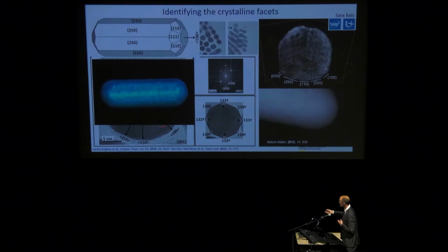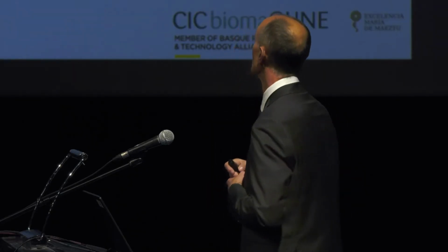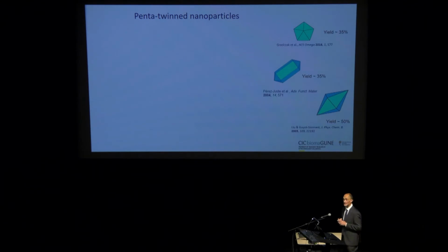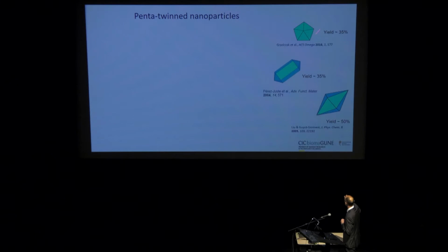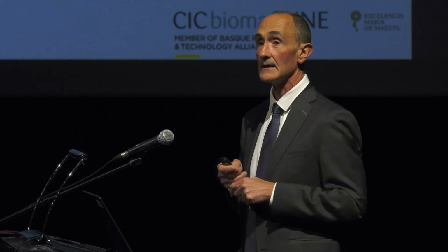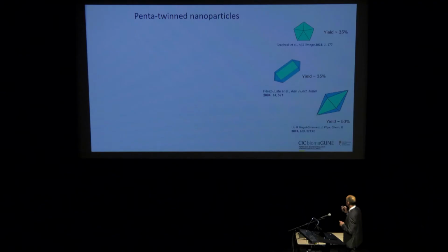This is one of the reconstructions that show the 8 lateral facets, all of very similar dimensions, all high index. Now, for the pentatwin nanoparticles, this has been a difficult subject, mainly because making seeds that are all pentatwin is very tricky. We have been working on this, making the decahedra, the nanorods, the bipyramids. The yields until very recently were always rather low. This means that if you see earlier pictures of pentatwin nanorods like this, you should be suspicious. In our 2004 paper, we show pictures like this, but with the complete image that also shows a population of spheres. This is because initially you have a mixture of single crystals and pentatwin seeds.